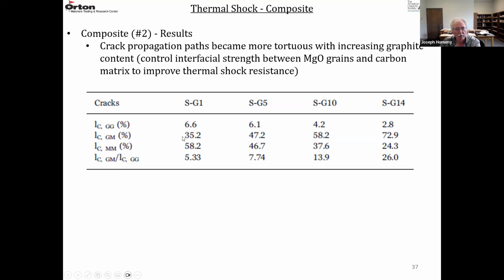And then through the interface, it starts out at 35% with the SG1, but as you go across this table to the higher graphite, it's now up to about 73%. So a totally different fracture path in the SG14 compared to the SG1. And then the matrix, it was 58% SG1 and it decreases to 24% in SG14. Then they made a ratio of the interface relative to the coarser grains. And that ratio increases from SG1 to SG14.